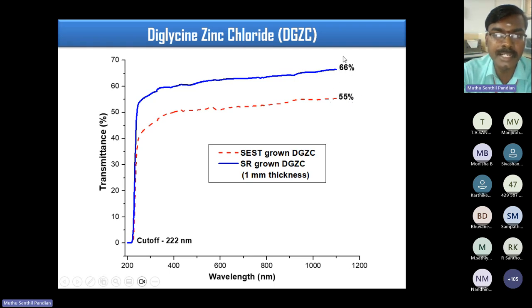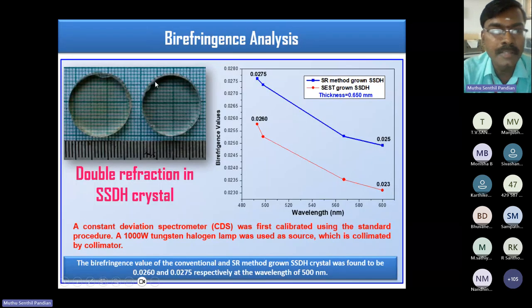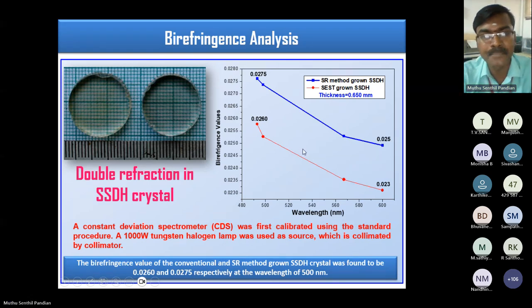Here, 11% higher optical transmittance in the SR method grown diglycine zinc chloride single crystal. And we have also performed the optical homogeneity of the conventional and SR method grown crystals, the pink colored crystal, the SR single crystal, and the optical homogeneity is also very high compared to the conventional method grown crystal.